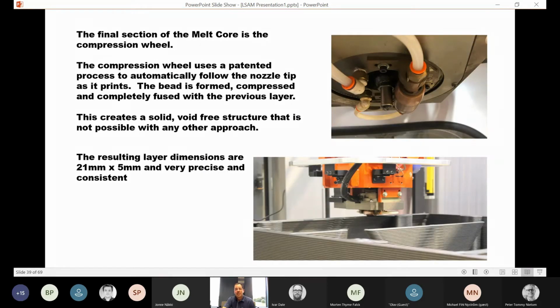The final section of the melt core is the compression wheel. The compression wheel uses a patented process to automatically follow the nozzle tip as it prints. The bead is formed, compressed, and completely fused with the previous layer. This creates a solid void-free structure that is not possible with any other approach. The resulting layer dimensions are very precise and very consistent. Those dimensions are 21 millimeters by 5 millimeters.